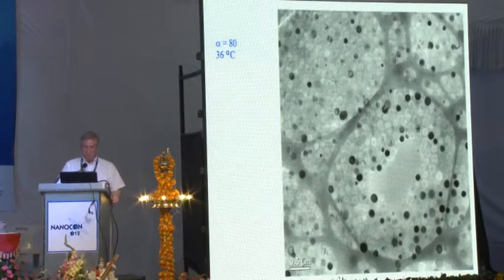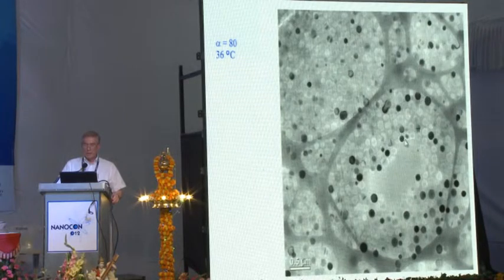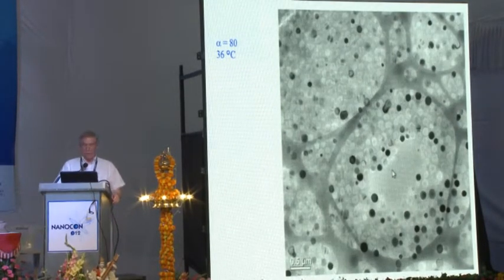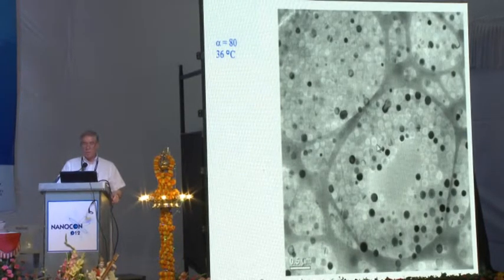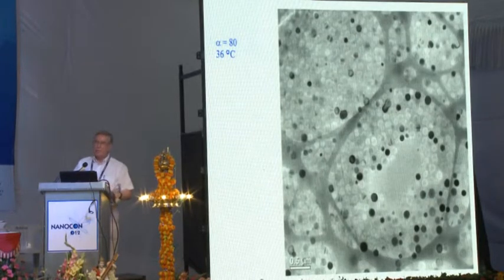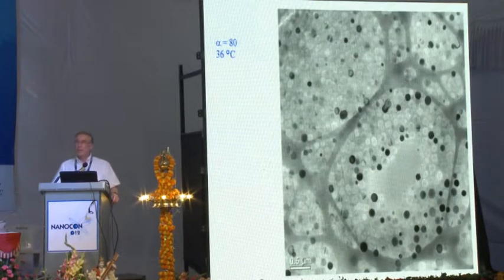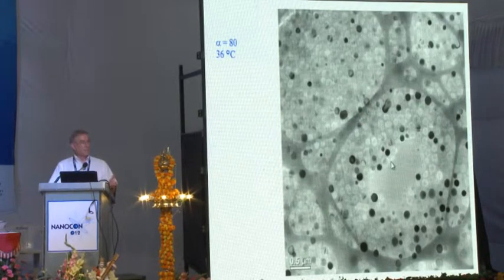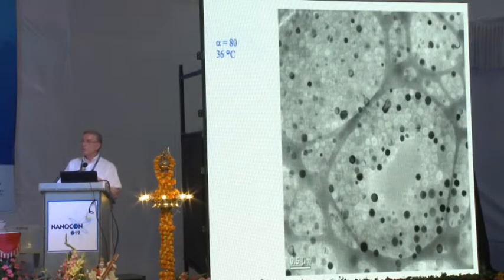This is the alpha 80, and what you see here are small droplets of water in a continuous phase of oil. The water droplets are sometimes dark, sometimes white. The reason for this is that this particular specimen was cooled in liquid nitrogen, which is a very bad cryogen, but we cannot use liquid ethane for this one, which will dissolve the octane. However, the octane that we used here was branched octane, and it vitrified very nicely. You see the background is featureless. However, the little water droplets freeze. They froze, and some of them are aligned with respect to the beam in such a way that they scatter electrons while others don't, and that's the difference in the appearance.